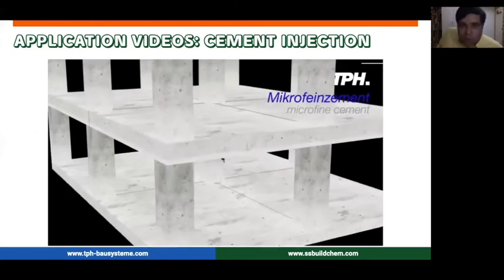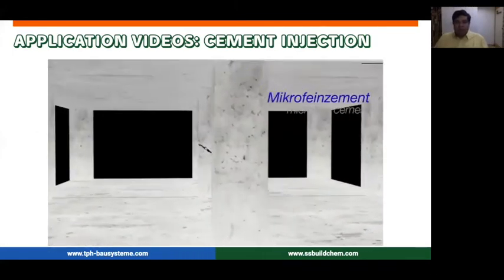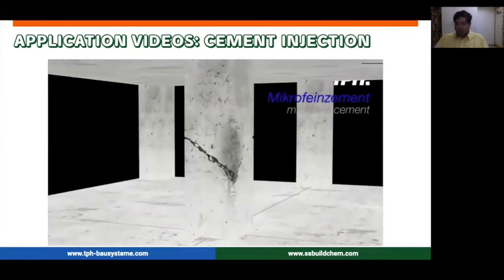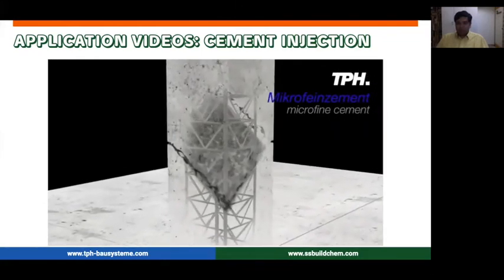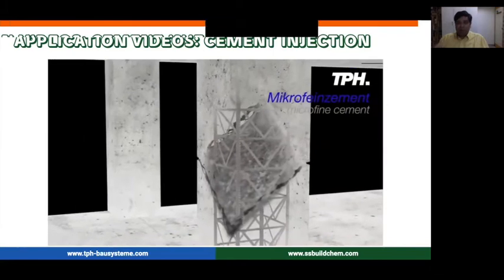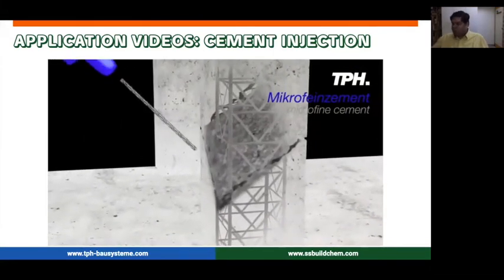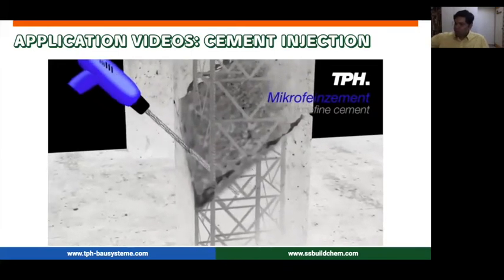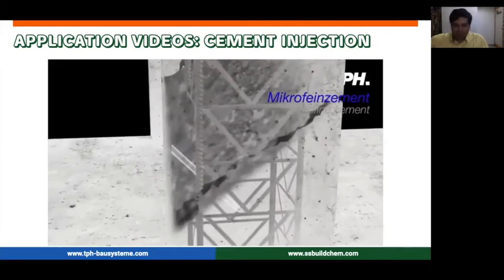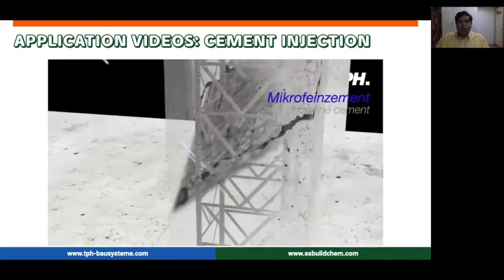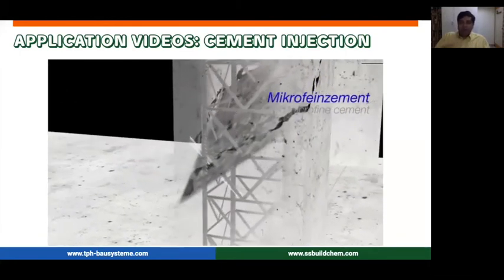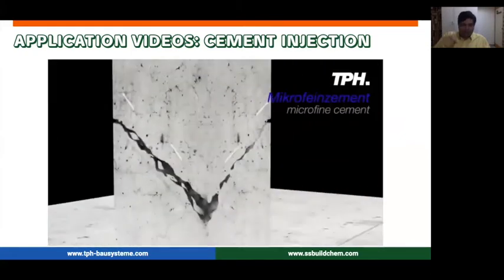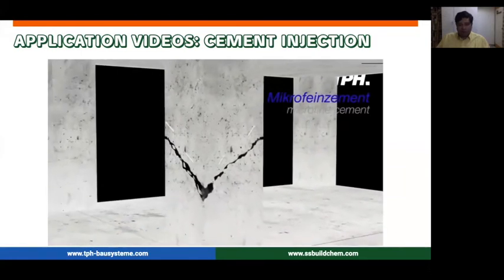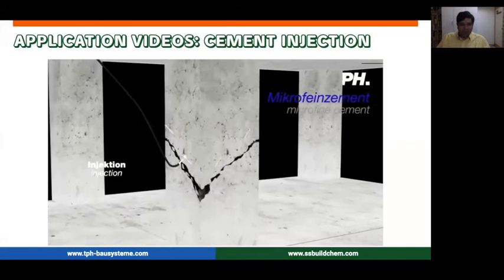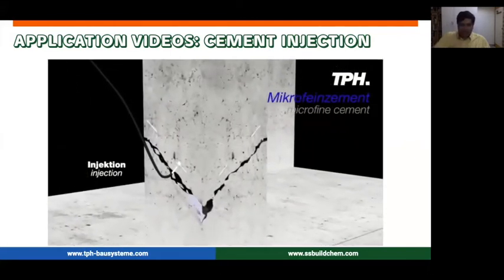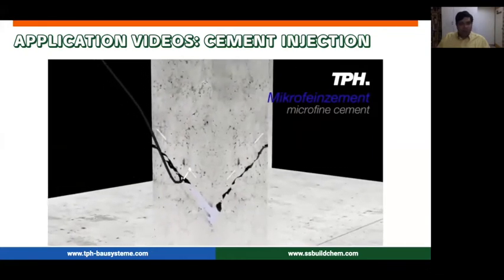Just a couple of quick videos for you to have a look at how we do the microfine cement injection, and the one that follows will be on both the epoxy system as well as the PU system. Normally, anytime you have cracks or even voids inside your structure, that void starts creating problems in the load distribution in your element. In that case, you have to make drill holes along the crack face. Make sure you're intersecting the crack. You normally cover up the crack, just for the graphic representation here they're not covering up the crack face. And then you pump in your material.